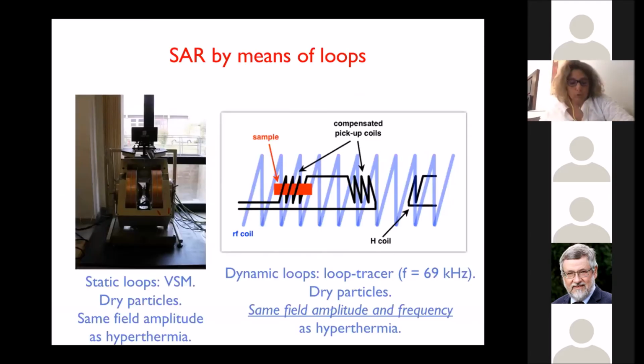Here I come to the magnetic properties. We have calculated the specific absorption rate by means of the hysteresis loop in two conditions. The static one by VSM, where we have worked with the same field amplitude as the magnetic hyperthermia setup. And here is the dynamical loop tracer that works at this frequency, and we have worked on the very same sample in these two cases.